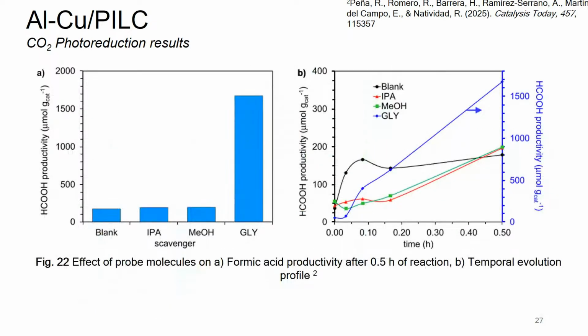And we also added some molecules to try to understand further the mechanism. IPA and methanol are usually added to scavenge the hydroxyl radicals and see the importance of those radicals. Well, it was surprising, but we didn't observe any difference here. While with glycerol, we observe an important difference.